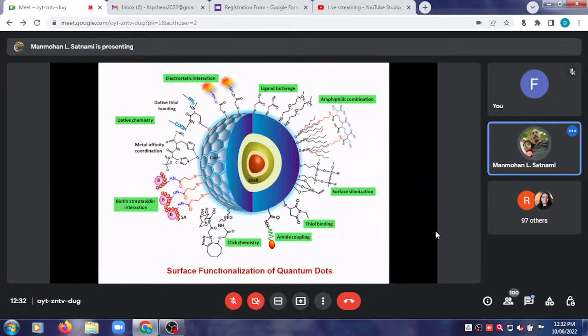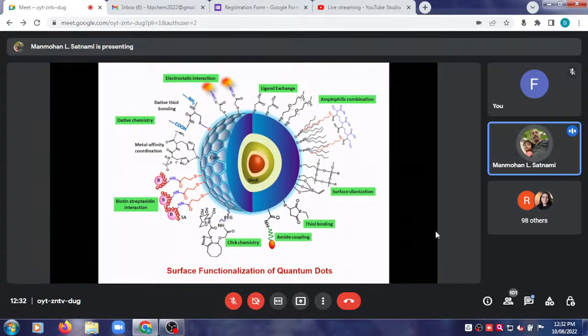Interaction could be different. If the surface of this quantum dot is negatively charged and any biological molecule is positively charged, then there could be electrostatic interaction. But if any biological molecule contains a carboxylic group and we have functionalized this surface with an amine group, then there could be amide bond formation between the biological molecule and this quantum dot, so that the biological molecule can bind with the surface of quantum dots, and whatever application you want to perform, you can do it.